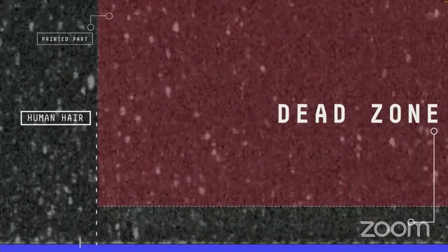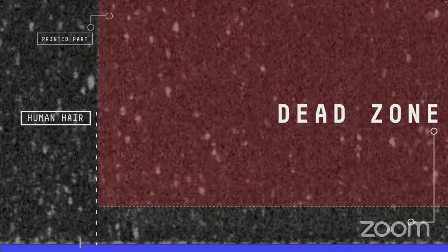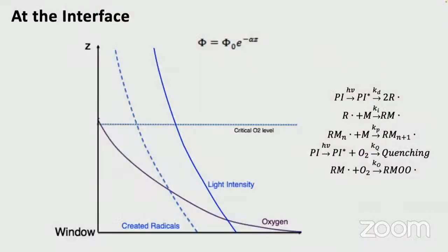This is not an adhesion issue. There's a mistake in the literature when people think about this as adhesion. This is a mass transfer issue. How do you get resin to the deepest pixel? And that's the key to these processes. Oxygen gives you the ability to replenish liquid without going through a traditional layer-by-layer approach. So this is really a mass transfer issue.